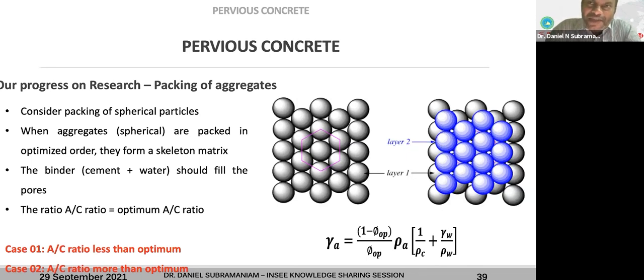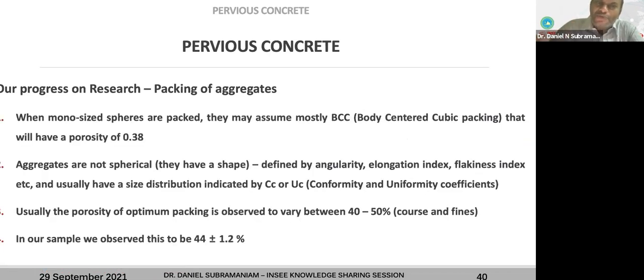What happens is, if you have an aggregate to cement ratio less than the optimum ratio, then when you are compacting, the aggregate particles will move closer to each other. It will squeeze the binder out of the path that it's going to move. If your aggregate to cement ratio is lower than the optimum, then you will have more cement or more binder in the cube. So what will eventually happen is the excess binder will be evicted from the cube. So even though you use an aggregate to cement ratio of, for example, about 1, if you do the compaction, you will end up with the optimum aggregate to cement ratio.